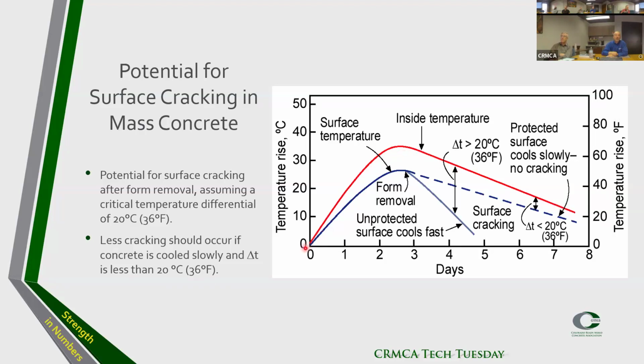We see that's the inside. The blue line shows the surface temperature, a little bit lower, but if we remove the form, or almost I would say the insulation, after 3 days, that temperature starts dropping faster than it's supposed to, and there's the potential that we're going to get above the 36 F difference, and there we might have surface cracking. So it is really wise to keep the form in place so that the temperature remains higher, and that gradient, that difference in temperature, does not exceed 36 F.